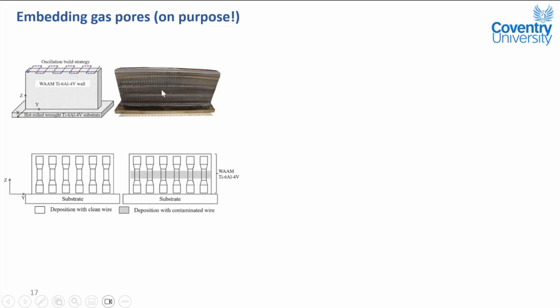So for the wire arc additive manufacturing, can someone confirm you can see the mouse movement? Yeah. Okay, so for the wire arc additive manufacturing, we use a clean wire to produce the samples on the left, but we also use contaminated wire deliberately with some greasy oil, and we produce the gauge length of our tensile samples. This has been a real problem for people not using clean wire. When they look at the fractography, they found more gas pores. So this was deliberately designed experimental work for PhD projects.